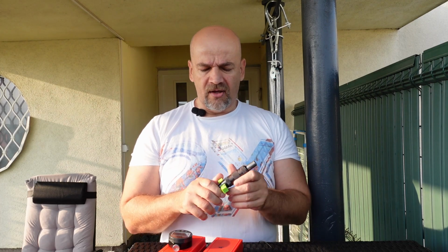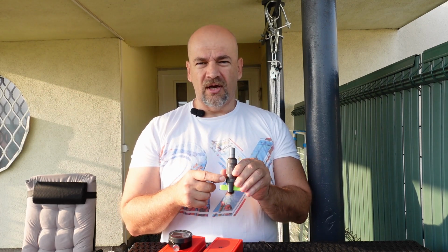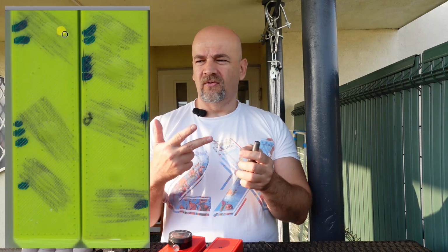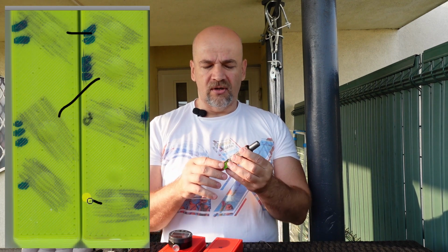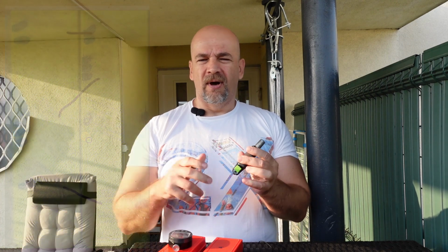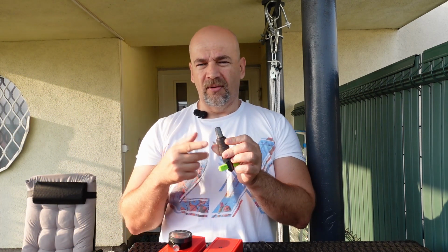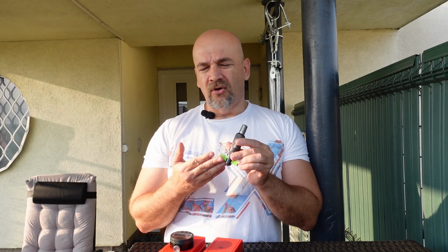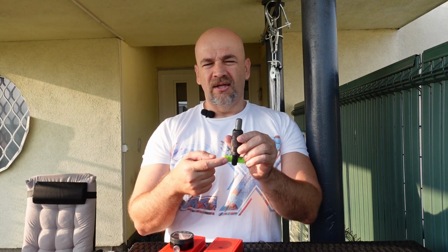And in the last experiment I tried to measure the hardness with this Poldi Hammer, and it was a very pleasant surprise to see those first three hole pairs are very equal with each other. So theoretically this could work, but when I tried to measure the PETG with this Poldi Hammer and used that equation and compared it to the hardness which I measured with the Shore Durometer, I got completely different results, and that's normal actually, because these two scales, the Brinell and the Shore D, are completely different. So this method could work only if you know the hardness of the reference material in Brinell, but nowadays nobody wants to measure the hardness of 3D printed plastic in Brinell. Everybody wants to know it in the Shore D scale.